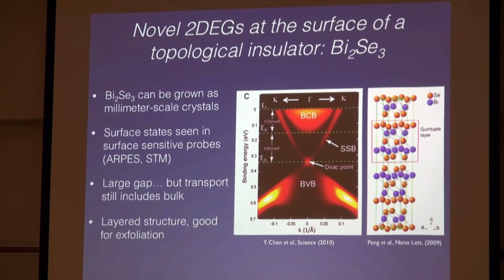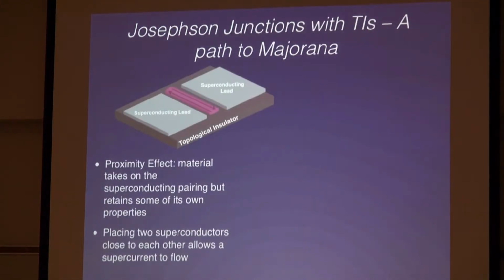And the main reason that people are still working on this, I think, is that there's a large gap, but they're always so doped, mainly due to selenium vacancies, I think, for bismuth selenide. They're so doped that the bulk still contributes to the transport. And you can see this. You look at the Fermi energy here. You have the surface state, which is at the Fermi energy, but you also have this very large bulk conduction band. So when thinking about measurements in the system so far, you always have to think about the bulk as being part of what you measure in transport.